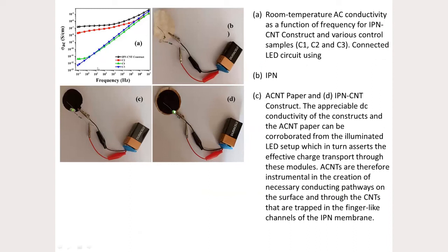So just to show you how the conductivity changes when we make different constructs. The IPN construct shows bulk conductivity of the order of 10⁻⁷, whereas the surface conductivity, as I showed you, was as high as 92 Siemens per centimeter. An LED bulb can also glow, which also means that the surface conductivity is very high.